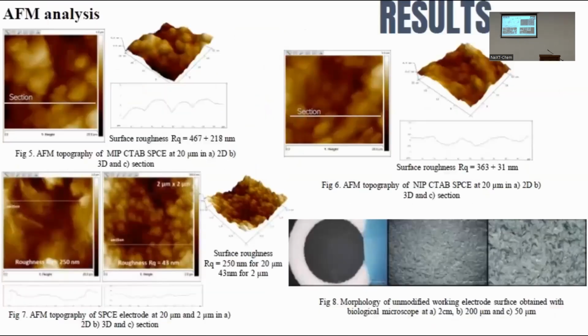The obtained MIP and NIP sensors were also subjected to the topographic AFM analysis. Due to the similar composition of the pastes, only MIP CTAB SPC analysis is presented here. Regarding the topography of the unmodified working electrode, a smooth surface can be observed with a relatively low roughness. The roughness at 20 micrometers is probably obtained due to the porosity of the working electrode, as it can be seen in figure 8.